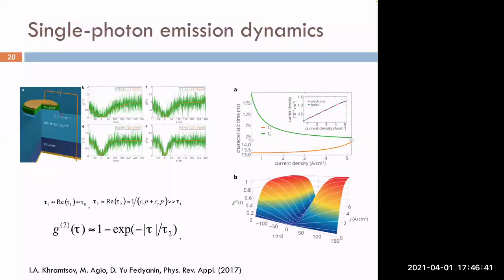So we also investigated the single photon emission dynamics, which is based on the theory that I described before. And so in this case, we are calculating not the emission rate, but the photon correlation that I described before in the Hanbury Brown and Twiss setup. So in this case, again, the process of bringing charges to the color center makes the photon statistics quite different than under optical pumping. And this is because the correlation is also now dependent on these capture processes of electrons and holes.